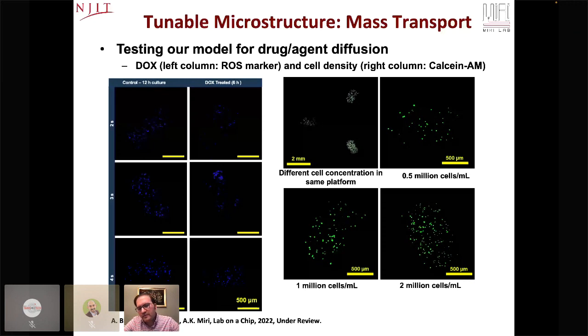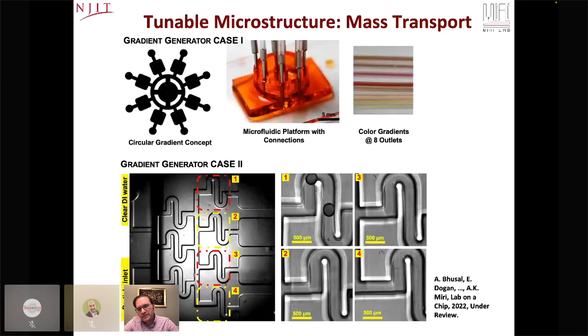Or another aspect that we can play around in our system is changing the cell density. You can change the cell density in each of the 3 chambers, and each chamber can be representing one specific case that can represent a healthy tissue, or it can be abnormal tissue or a diseased tissue. And again, this is not only limited to 3, it's scalable. When you're going to increase the number of chambers, you can use the circular design to add more chambers into your system, and you can add another circle at another layer, so you can increase the numbers going from 3 to 8, or from 8 to 8 to the power 2, for example. You can always increase the numbers in a hyperbolic way.